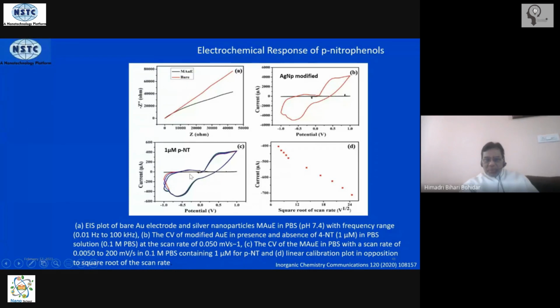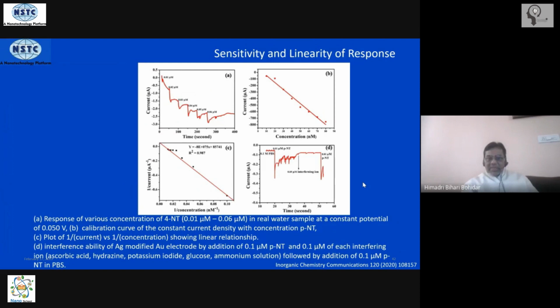Now when you expose it to the analyte, you see there is a specific anodic current, also a specific cathodic current here. And again, to ensure that the electron transfer process is diffusive, you plot either the anodic or cathodic current as a function of the square root of the scan rate, and you get a straight line, which is seen here. This again says that you have a diffusive process of electron transfer inside the material, and the material is exhibiting redox reaction. And now from the analysis of your electrochemical data, you should be able to create a calibration plot for this one.